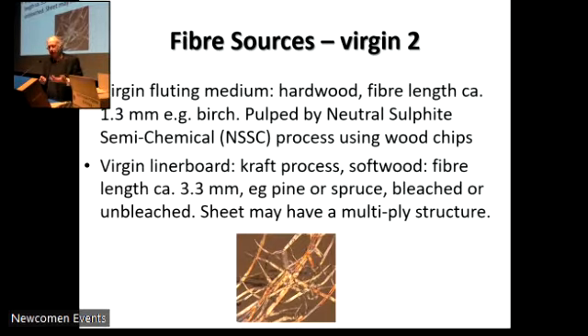We pre-treat the chips made from the tree with a chemical liquor containing sulfur dioxide, which depolymerizes the lignin and enables us to free the fiber from the lignin in a device called the refiner, which is a bit like an old-fashioned millstone, except the discs are orientated in the vertical plane. They have bars between them. One disc rotates at high speed, and as it does so, it brushes and defibrillates the chips and frees the fiber from the lignin. And that's known as a neutral sulfite semi-chemical process, or NSSC to aficionados of the sport of corrugated containers.